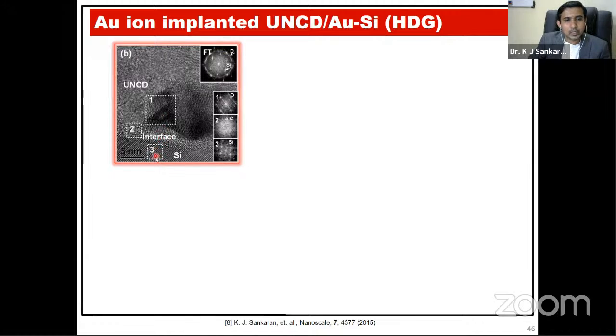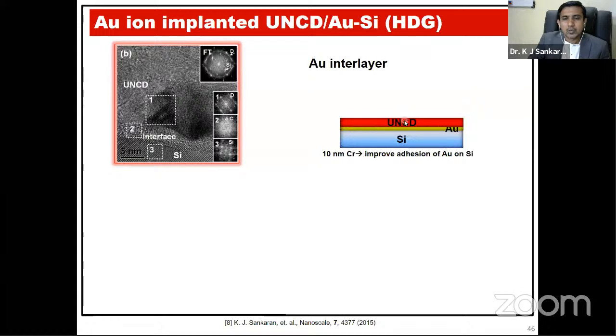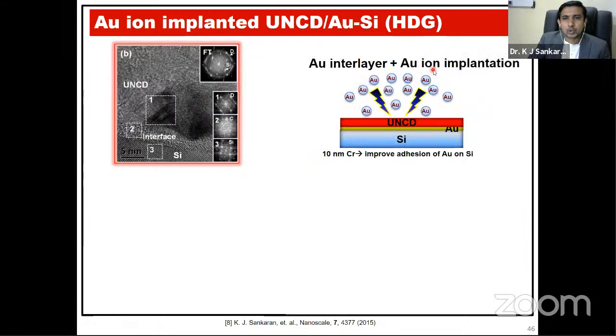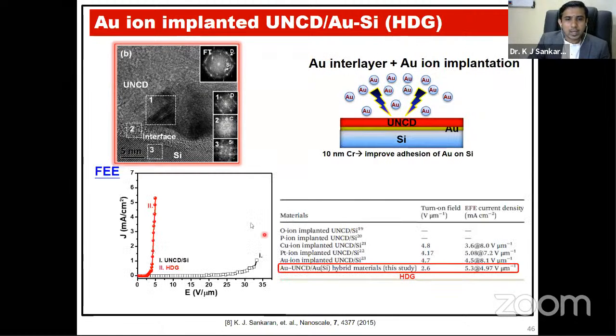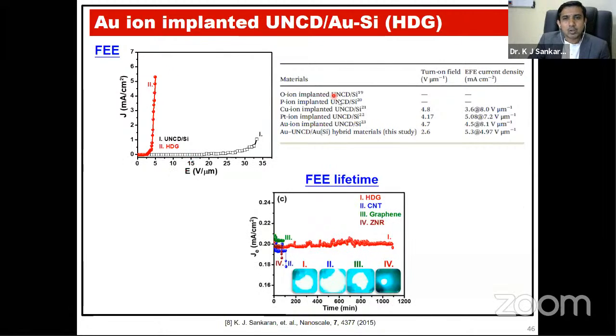But the interface should also be considered for the transport of electrons from silicon to the UNCD. How can we do that? So we used a gold interlayer between UNCD and silicon, and then we implanted with gold. With the gold interlayer and gold ion implantation, we achieved a low turn-on field of 2.6 with high current density. To know the reason why, and how this gold reacts with UNCD and silicon at the interface, and how the gold ion implantation makes field electron emission efficient, we carried out TEM. The lifetime stability was also compared with other well-known field emitters, and we found that this hybrid diamond with gold material shows very good lifetime stability, more than 1000 minutes, as compared to the other field emitting materials.